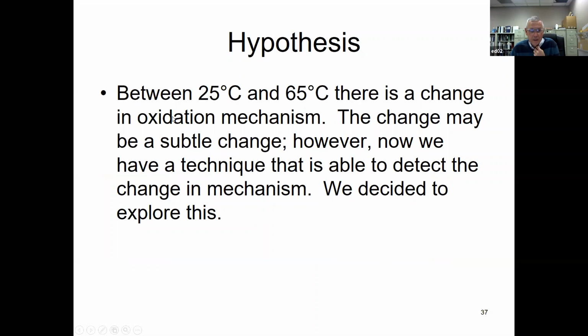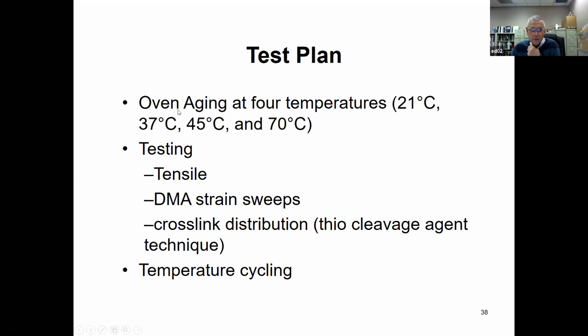Okay, so the hypothesis is between 25 degrees and 65 degrees C, there is a change in oxidation mechanism. The change may be a subtle change. However, now we have a technique that is able to detect the change in mechanism. We decided to explore this. Okay, so the test plan is oven aging at 4 temperatures: room temperature, 37 degrees, 45 degrees, and 70 degrees. And the testing included tensile, DMA strain sweeps, and crosslink distribution using the thiol cleavage agent technique. And then in the end, I'll describe an experiment we call temperature cycling.